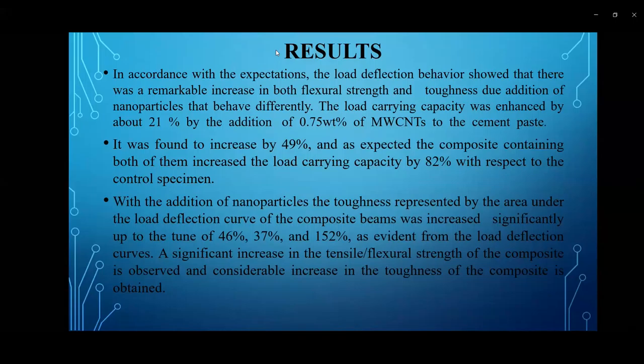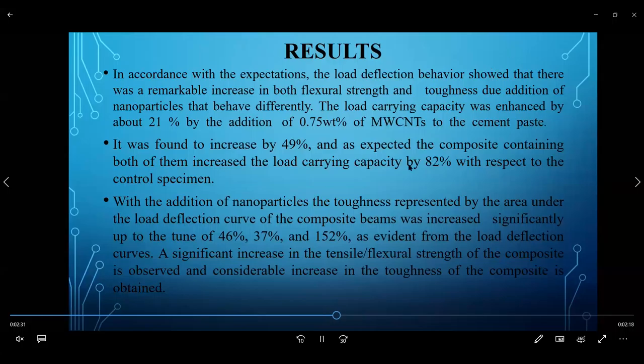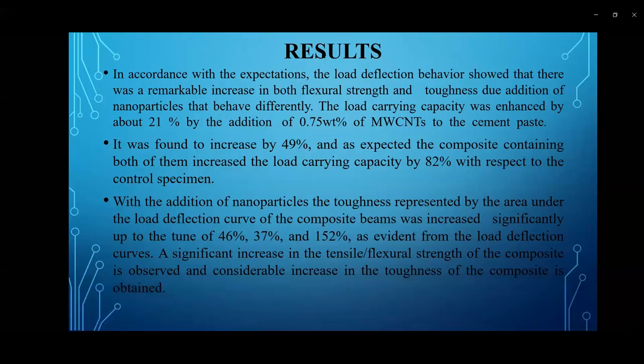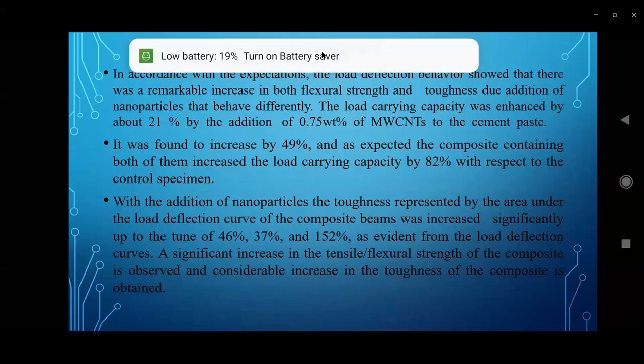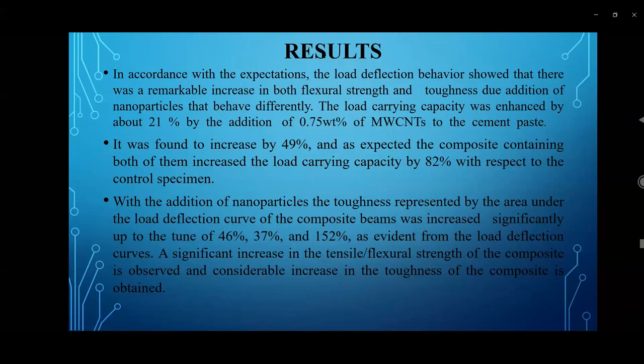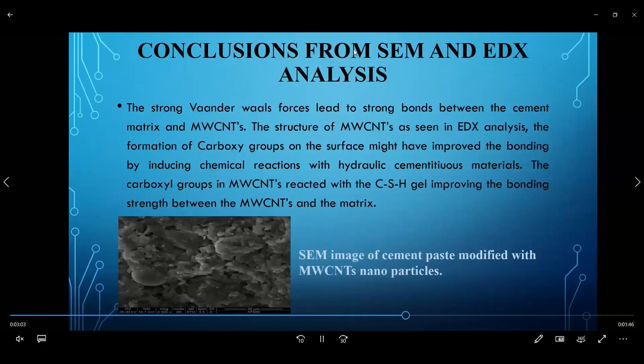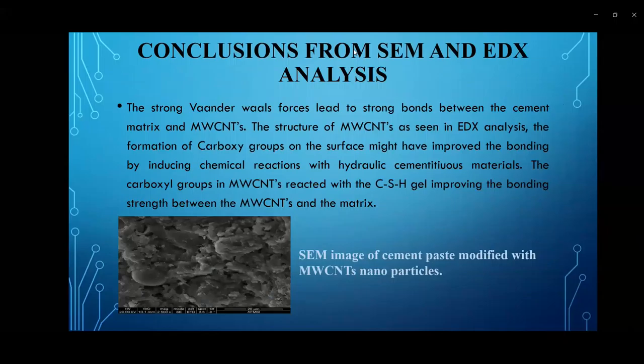The load carrying capacity was enhanced by about 21% by the addition of 0.75% of MWCNTs to the cement paste. With glass fibers it was found to increase by 49%, and as expected, the composite containing both of them increased the load carrying capacity by 82% with respect to the control specimens. With the addition of nanoparticles, the toughness, represented by the area under the load deflection curve of the composite beams, increased by 46% and 152%, as evident from the load deflection curves. A significant increase in the tensile and flexural strength of the composite is observed, and a considerable increase in toughness of the composite is obtained. These are the SEM images we have got by mixing the MWCNTs and glass fibers.